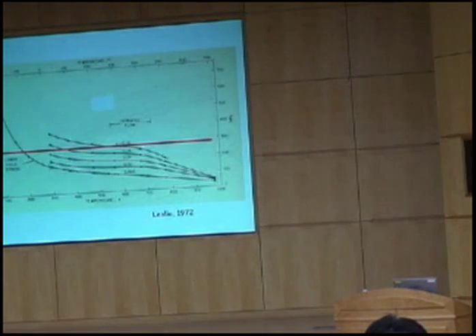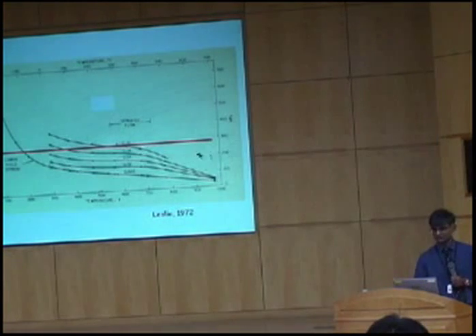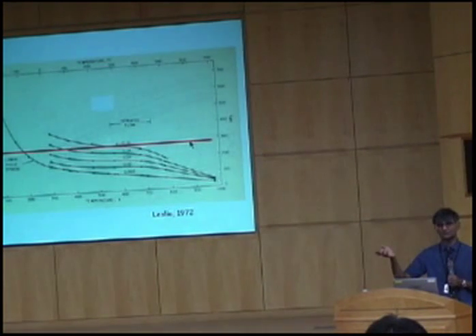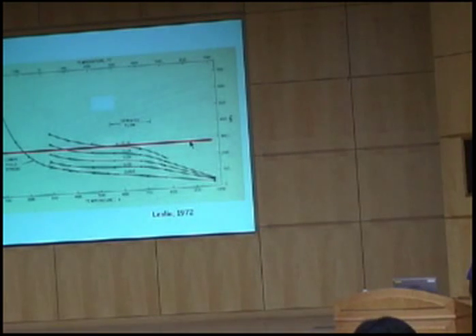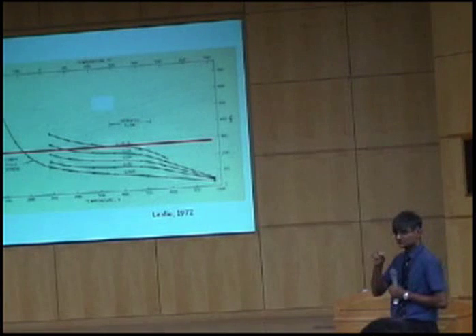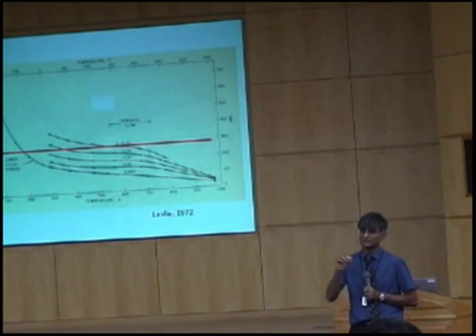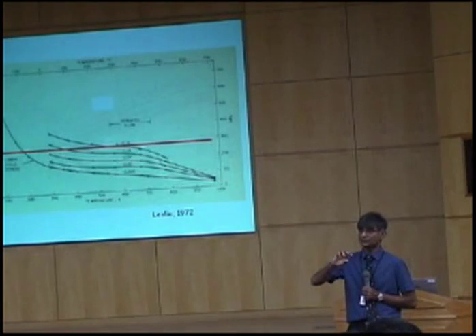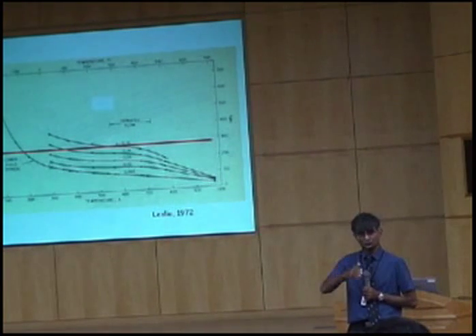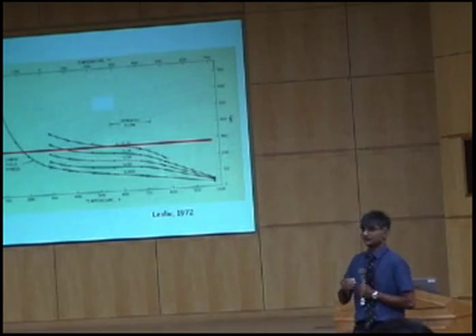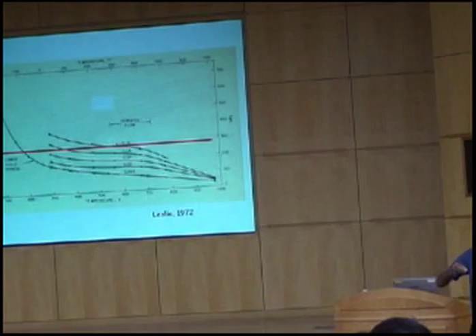Okay? This is an oversimplified diagram. The cleavage strength is not constant. If you change certain things inside your lattice, for example if you change the composition, say the nickel concentration, then the cleavage strength increases. And the reason why the flow stress is very sensitive to temperature is that dislocations in ferrite are actually dissociated on a very, very fine scale. They are dissociated in three dimensions. So they require quite a lot of activation in order to move from one position to another. And the way in which alloying elements influence that dissociation determines the ductile brittle transition temperature.